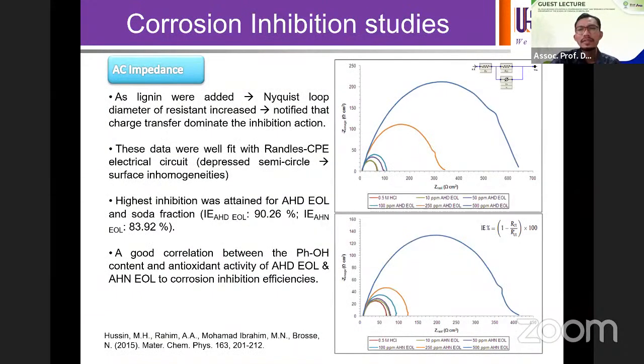So what we did was, after we obtained the modified lignin, we prepared it in different concentrations. We studied the corrosion inhibition via electrochemical methods. So we performed electrochemical impedance spectroscopy. And what we obtained was that as we increase the concentration of the modified lignin inhibitor, it provides us with higher charge transfer resistance values. So this indicates that as you add the modified lignin into the solution, it can retard even more corrosion of mild steel in this case. And the inhibition efficiency was attained at more than 90% inhibition.